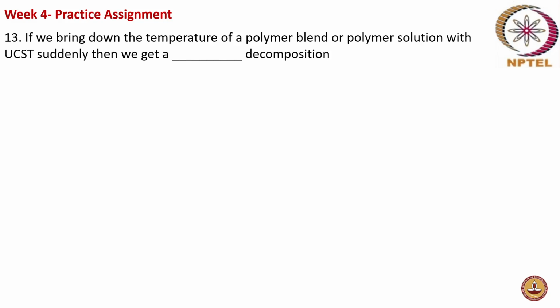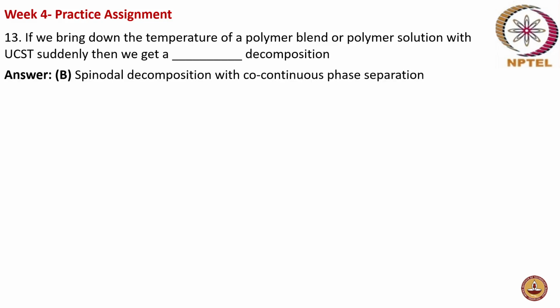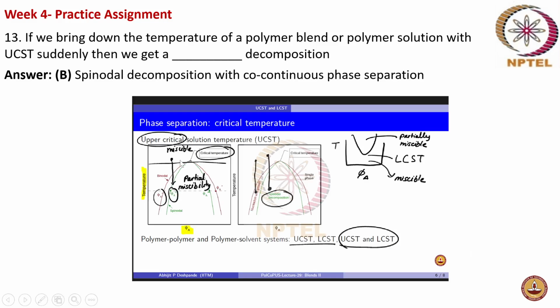If we bring down the temperature of a polymer blend or polymer solution with upper critical solution temperature suddenly, then we get a dash decomposition. What kind of decomposition happens when we bring down the temperature of a polymer blend or polymer solution with upper critical solution temperature? No idea. Okay, you start getting a spinodal decomposition with co-continuous phase separation. So this is a system having upper critical solution temperature, so temperature versus volume fraction. Above the critical solution temperature, the system is completely miscible. So as you bring down this temperature, there are two kinds of decomposition generally possible,